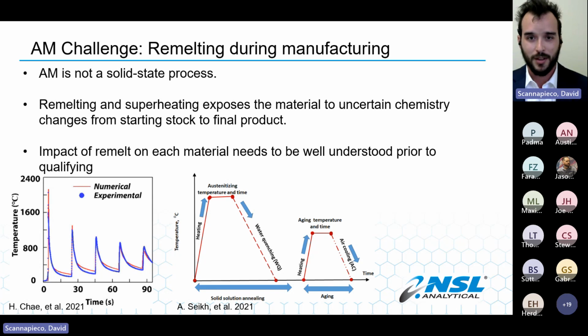And yes, we're working in an inert atmosphere, but even at 0.1% oxygen partial pressure in the chamber, which is where a lot of additive manufacturing machines will start printing at, you end up with oxides in the material because liquid metal loves oxygen. And even worse in some cases, the unintentional chemical gradient part, we superheat the metal. So it's not just getting it into a molten state, but superheating it, and in many cases vaporizing it. You see that on the inside of additive manufacturing machines, you get coats of whatever metal you're working with, on an atomistic level, but it does exist. And that can make some uncertain chemical changes from our powder stock to our final product.